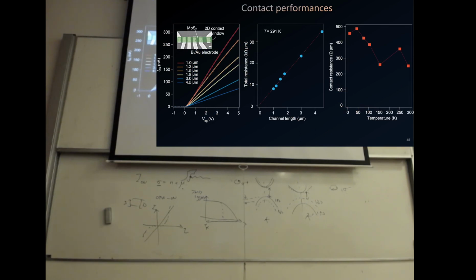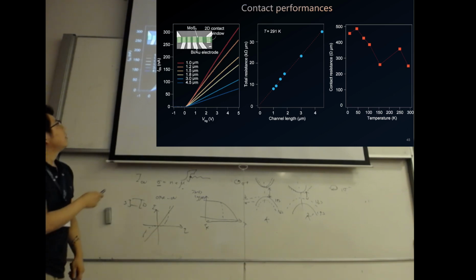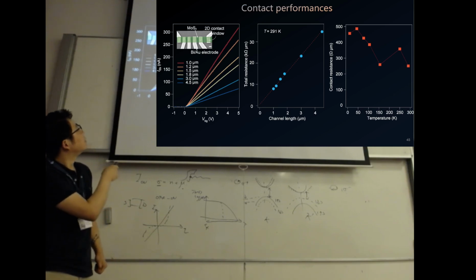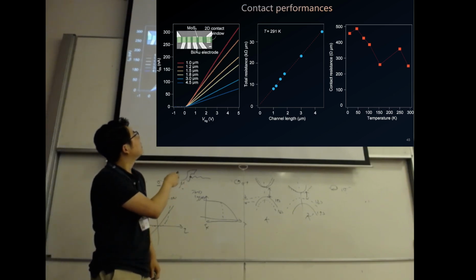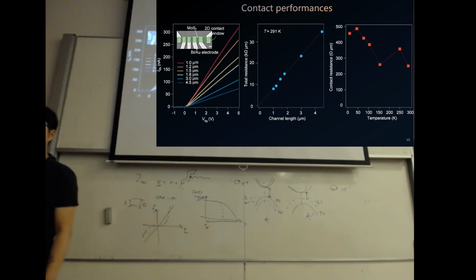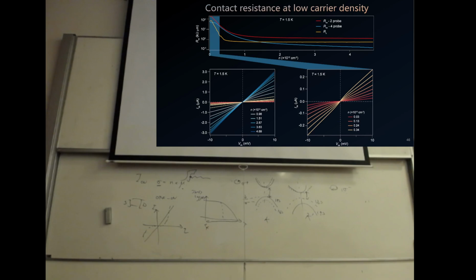This is how it looks. You can see the field effect curves of the transistors at different lengths. We have a window-contacted stripe of MoS2, in green color, and along with this shortening of channel length, the on current is increasing, which is expected. Then we have the total resistance extracted by the TLM method, and we can measure the contact resistance as a function of temperature. Even though we cool down from 300 Kelvin to 1 Kelvin, the contact resistance is always only a few hundred ohms, never exceeding 500. That's the best contact we can obtain using a very simple method combining three tricks together. And then we can have further characterization at 1.5 Kelvin.